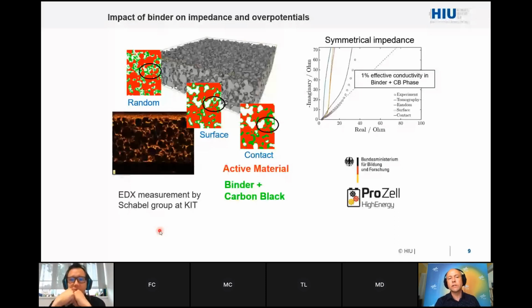If you distributed them randomly on this tomography, which we had at our hands, we couldn't see the binder. So we only knew how much binder was in the tomography. Therefore, we decided that we just test different configurations. So we used a random one where the binder was distributed on the surface, and another one where we concentrated the binder in the contacts, in the necks between pores. And this is, for example, a picture of the binder distribution due to binder migration from the group of Schabel at KIT. And what we found is that depending on which distribution we choose, we get a different result for the impedance spectroscopy simulation.